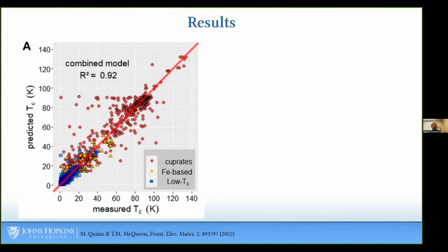These are actually not issues with the model per se. They're issues with the data that we're comparing to. Because many of these points that are these big outliers here, they are things where the chemical composition was not figured out at the time. And in hindsight, we know, for example, that oxygen content matters a very great deal for the superconductivity of yttrium barium copper oxide. But many of these points have essentially the same composition because it wasn't determined analytically at the time.